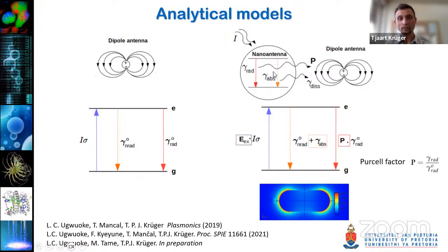Now, when this dipole antenna couples with a nano antenna, a plasmonic nano antenna, then one gets excitation enhancement. So one will have to multiply this absorption rate with an enhancement factor. The radiative rate is also enhanced by the so-called Purcell factor. And there's an additional non-radiative decay term that arises from energy transfer from our molecule, like LHC2 in this case, to our metallic nanoparticle. And most of this energy that's transferred is then thermally dissipated in the metallic nanoparticle, causing Joule heating. So that is also non-radiative. Okay, so from this one can calculate the fluorescence quantum yield, and one can model the absorption and fluorescence spectra. So we've done all of that. Not going to give you all the details in this specific talk. Just the last two slides before I'm done.